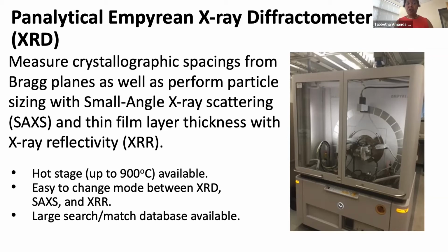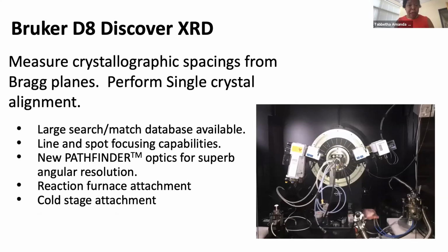With the small angle X-ray scattering, you're able to get particle sizing in the range of nanometers, in tens of nanometers up to hundreds of nanometers. The other unique feature of this instrument is that it's equipped with a hot stage, so you're able to do temperature elevations and analysis of your samples in situ at these elevated temperatures. And of course, we have all of the search match databases available for you. Now, the other diffractometer that we have is a Bruker D8 Discover, and this is able to do alignment of single crystals and many of the other diffraction features that are on the other instrument.